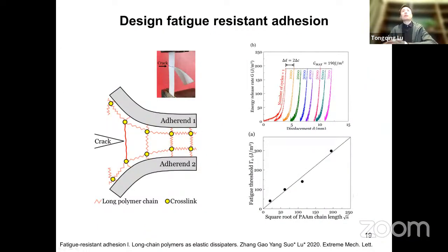After we confirm that this long chain strategy is very effective, now we can use this strategy to design some fatigue resistant material or fatigue resistant adhesion. So for example, there are 2 materials here, we demonstrate with 2 pieces of cloth. There's an interfacial crack here. So how to improve the fatigue resistance of this adhering interface? As we demonstrate, very simple. We just introduce some polymer chains to interlock with the two pieces of cloth. As long as we use very long polymer chains, we believe that the fatigue threshold of this interface will be very high. So as we predicted, here's our experimental result.